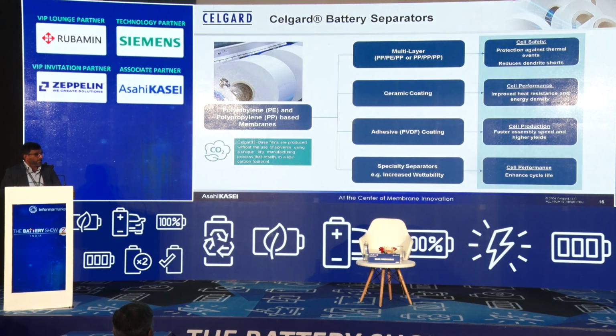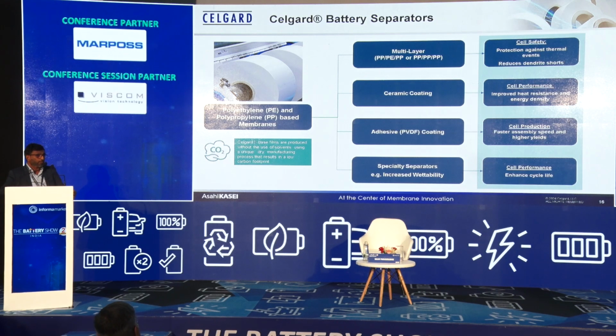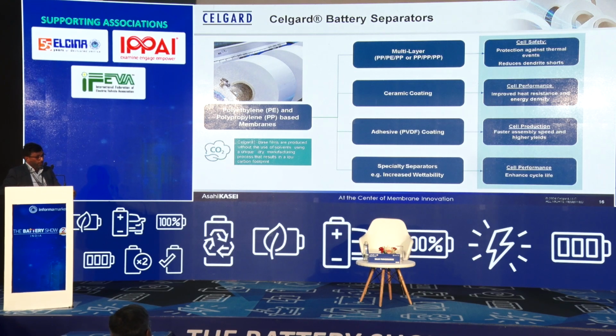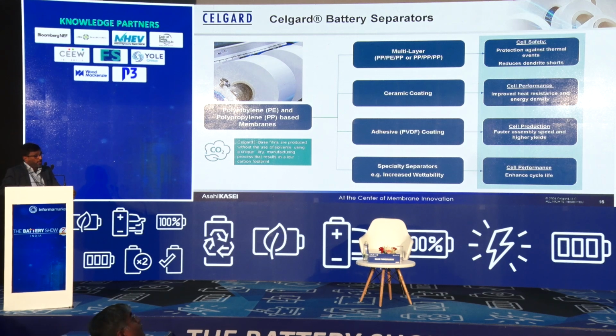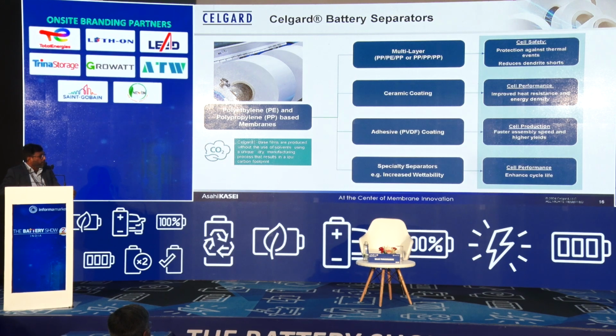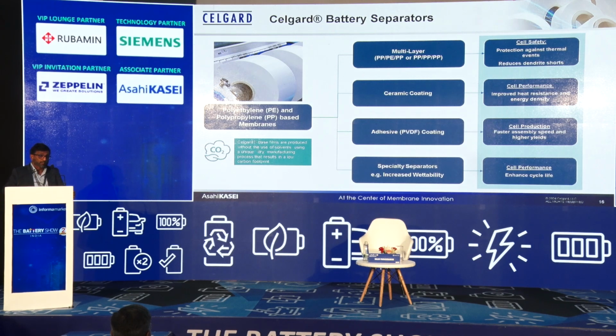And to summarize, Celgard has the ability to make multi-layer separators, with polyethylene sandwiched between polypropylene to give a tri-layer. It can also do a multi-layer polypropylene, to reduce dendrite shorts and act as a fuse. It can also have a ceramic coating for improving the cell performance, and adhesive coating and PVDF to increase the reliability, give faster assembly and speed, and reduce the rejection rates. And we also have specialty separators which can increase the wettability of the separators.